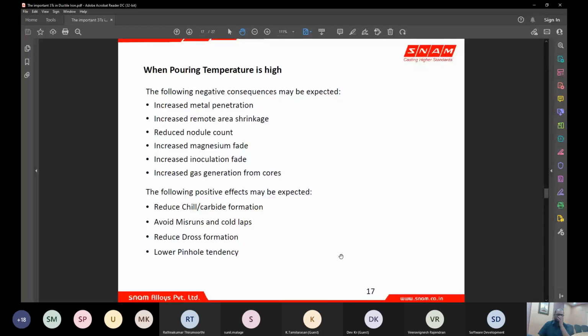So all the slag forming elements, and most of the elements in a ductile iron, like iron, manganese, silicon, and calcium, are low melting alloys, and these elements form oxides at a very low temperature, and these oxides become very stable at low temperature. So that means you should be able to pour just above a temperature where all these oxides will not be formed. So pouring at a low temperature is also dangerous, where you tend to form a lot of dross, and you tend to form a lot of gas defects, where you don't let enough amount of gas to be let out of the liquid metal.